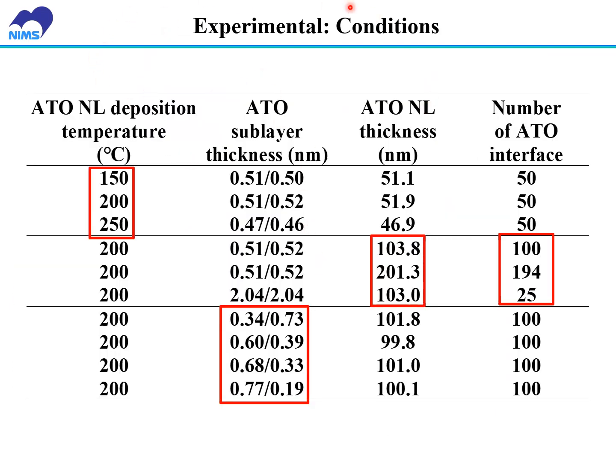We tried to change the experimental conditions to confirm their effect on the capacitor. We changed the deposition temperature for the ATO nanolaminates from 150 degrees C to 250 degrees C. We also changed the ATO sublayer thickness from 0.34, 0.73 to 0.77, 0.19 nanometer. We also changed the ATO nanolaminate total thickness from around 50 to 200 nanometers, and also changed the number of ATO interfaces from 25 to 194.